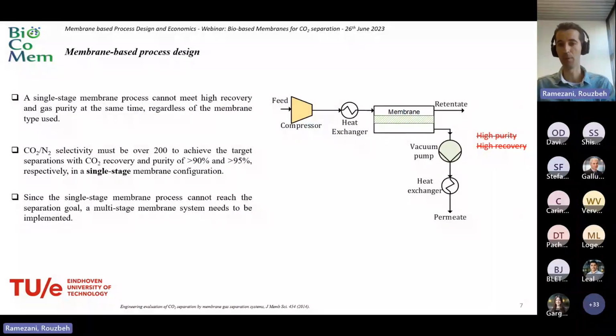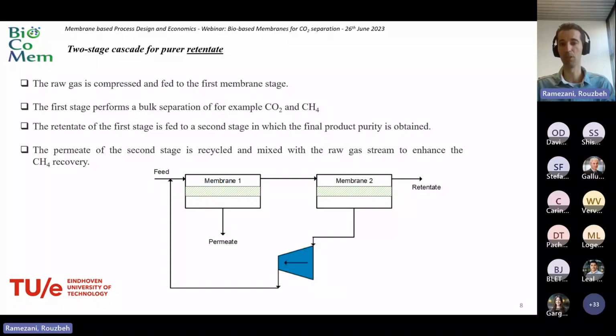But there is a challenge here in case you want very high purity or very high recovery. In a single stage, you cannot achieve that, or you need a very good membrane with very high selectivity. For example, in post-combustion CO2 capture, polymeric membranes now have selectivities of about 50, 45, 60. So you need a membrane with 200 selectivity to achieve that 90-95% recovery and purity in one single step. So what we can do is add another membrane cell. Let's see what happens in the two-stage membrane.